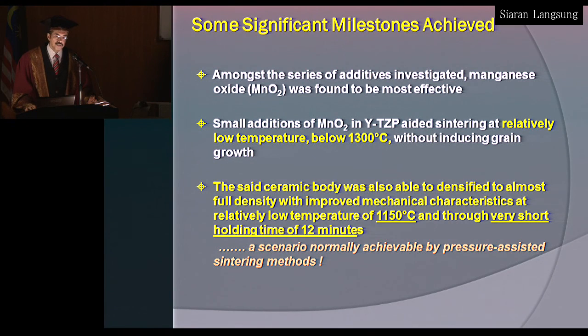All right, so what my group has found is that the use of manganese oxide is most effective. Small addition of MnO2 in the zirconia aided sintering at relatively low temperature, so that's one of the objectives. We are able to lower the sintering temperature without inducing grain growth. And the body is able to densify at even lower temperature and using very short holding time. And we managed to achieve 12 minutes holding time. Now, this scenario normally could only exist with pressure-assisted techniques like hot pressing or hot isostatic pressing. So you need pressure to be present during the sintering to achieve high density at very low temperature and at very short time.